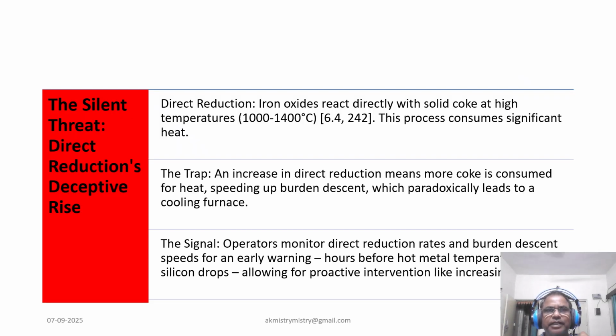Imagine your furnace is secretly cooling down, yet the hot metal flowing out still seems normal. The earliest, most critical signal often comes from something called direct reduction. This is where iron oxide, instead of being reduced by gases, reacts directly with solid coke at extremely high temperature, a process that devours heat. If the rate of direct reduction increases, coke is consumed faster and the solid burden descends more quickly, creating a domino effect that will ultimately chill the furnace.